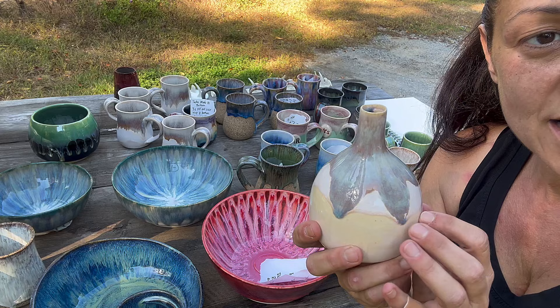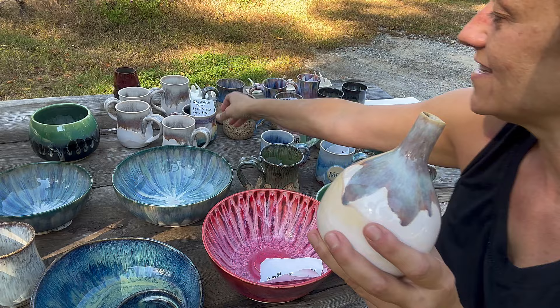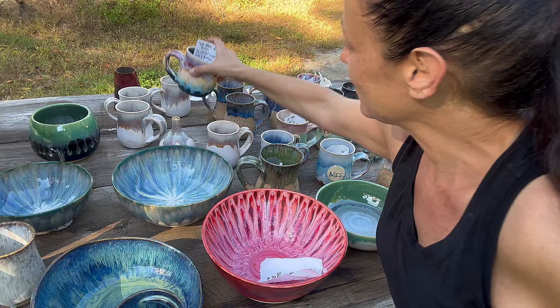This is Honey Flux and Iron Luster, but it was on the bottom shelf, so it didn't get super hot — it got to about cone five and a half. I noticed it didn't run as much as the middle shelf, which was like a hot cone six and a half, almost a seven. They're still beautiful.